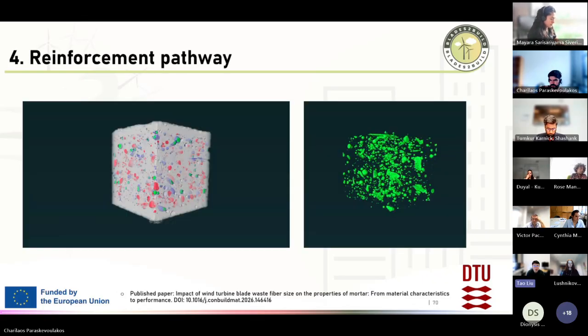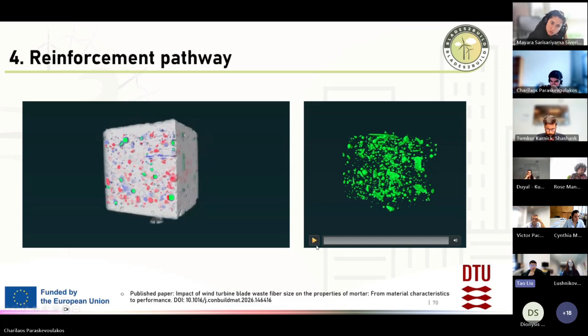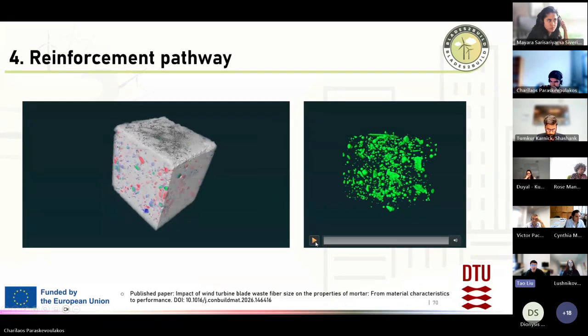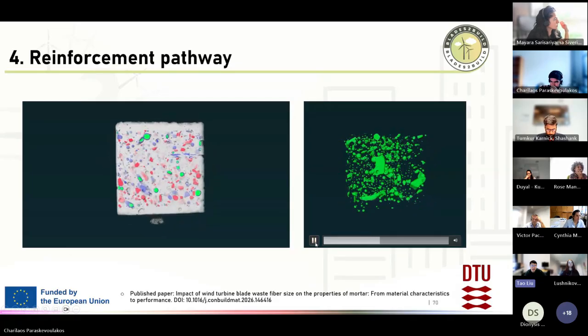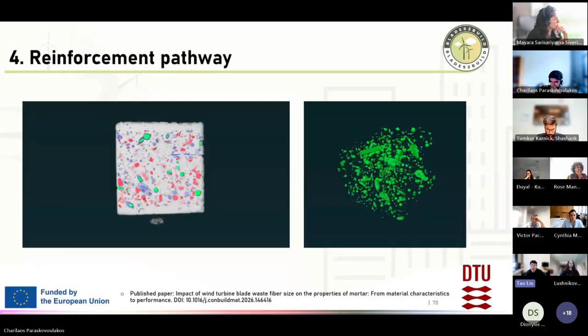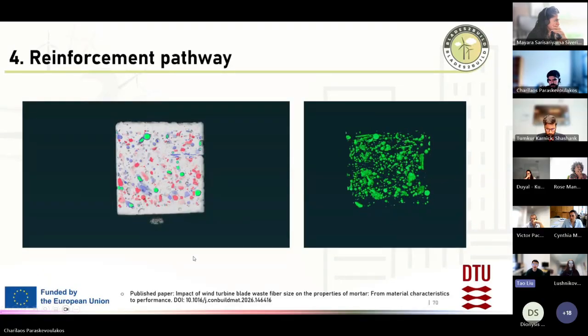For this fiber reinforcement pathway, we put the materials in the mortars, and then we cut the cubic materials to do the CT scanning to see how the materials are distributed in the mortars. The left side is the distribution of the materials in the mortars. The right one is the pores and the fiber distribution in the mortar. It's difficult to distinguish the pores and the fibers, because the fibers from the blade waste contain resins and glass fibers. The resin has relatively very low density, just like the pores. In the micro-CT, we can only identify from the shape of it instead of the density. Please, next one.